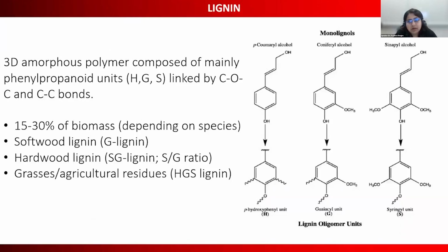So just briefly about lignin. Lignin is a 3D amorphous polymer, which is mainly composed of phenylpropanoid units. It is linked by carbon-carbon and carbon-oxygen-carbon bonds. There are three different types of lignins that you see in nature, depending upon the species, which differ in the monolignols, which themselves differ in the methoxy substitution at the 3,5 position. As you can see here, H, G, and S. It ranges from about 15 to 30% of the biomass, again depending on the species. Softwood lignin only contains G lignin. Hardwood contains S and G lignin. And grasses and agricultural residues contain HGS lignin.